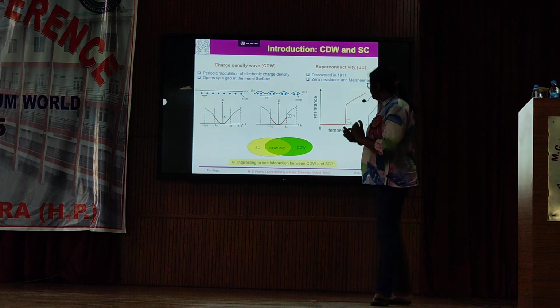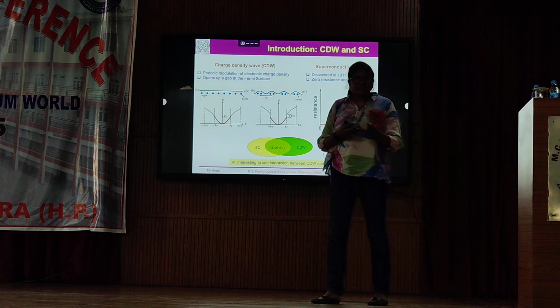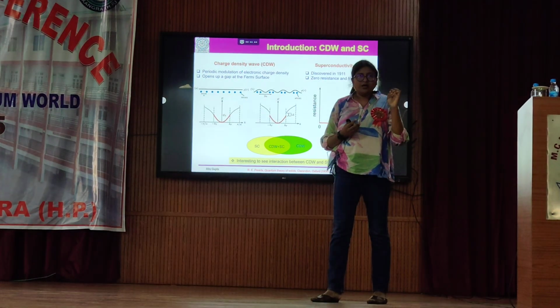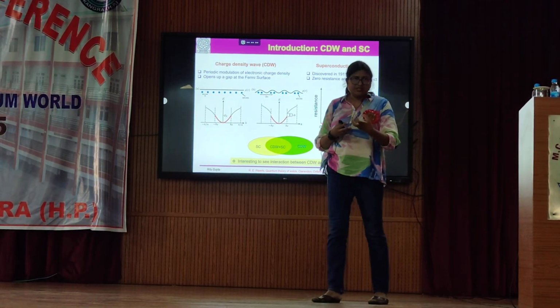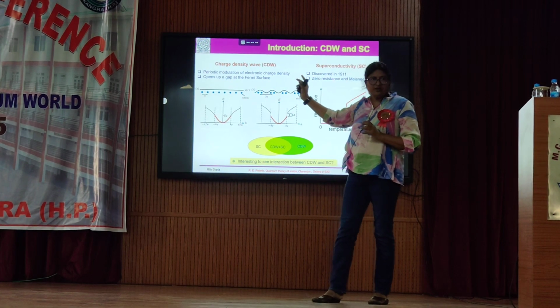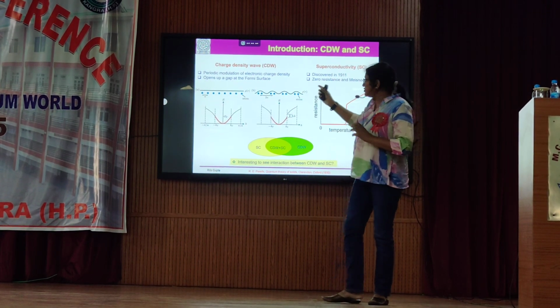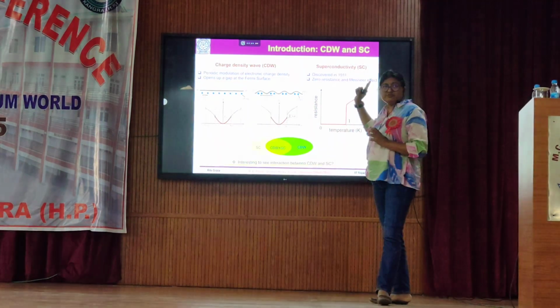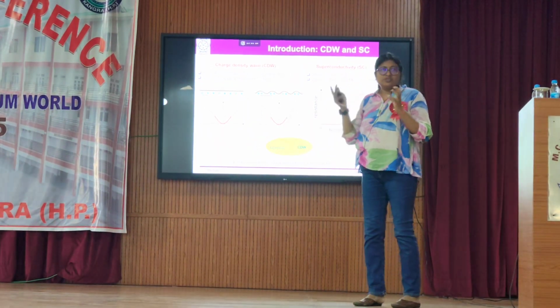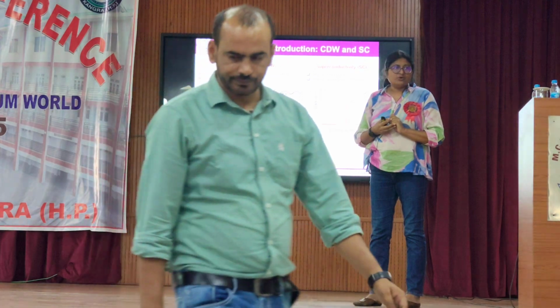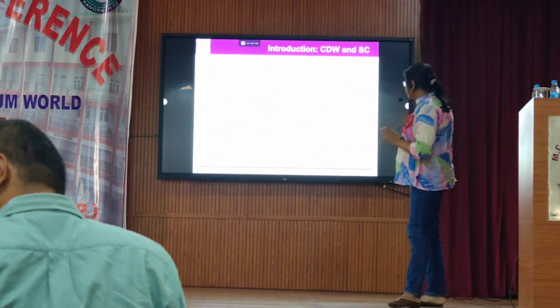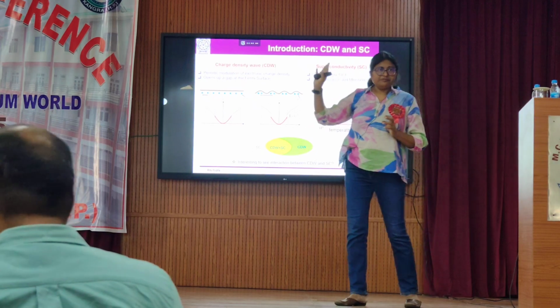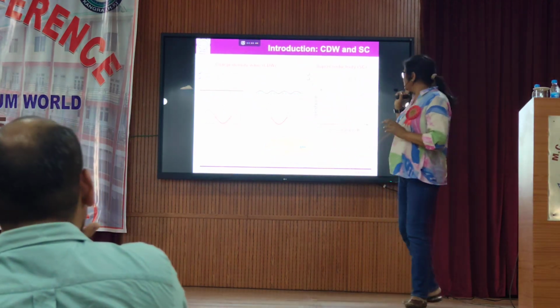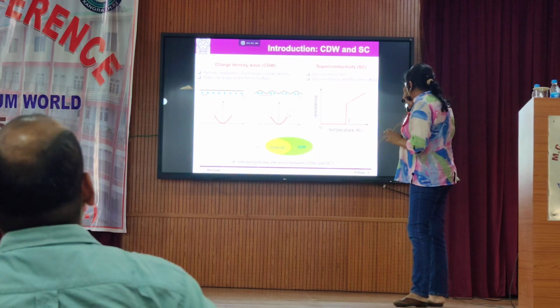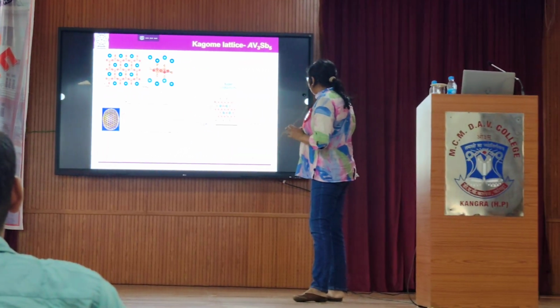So basically there is a partial opening of a gap at the Fermi surface. Some of the charge carriers are not participating in the conduction. Okay, this is what you mean when you have a gap at the Fermi surface. So this phase will be competing with superconductivity, because for superconductivity you want to have many electrons in your system, right? So Tc will be low, but if somehow you can suppress this charge density wave, you can get a very high Tc. Okay, so this is one of the phenomena I will talk about today.